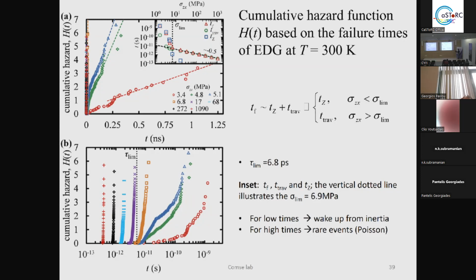So this, and also these behaviors, and also that we took the same behavior from what we saw before, that from these hazard plots, we saw that we have an exponential, somehow exponential behavior. And after that, an independent, roughly speaking, independent in terms of temperature and linear with an order of minus 0.5, which is a square root. So all these results lead us to the idea that maybe finally the time of failure is not only one parameter that Zhurkov introduced, but maybe it can be divided into two different times depending on the stress that you apply. And that's why you have the different behavior for the two different regimes.